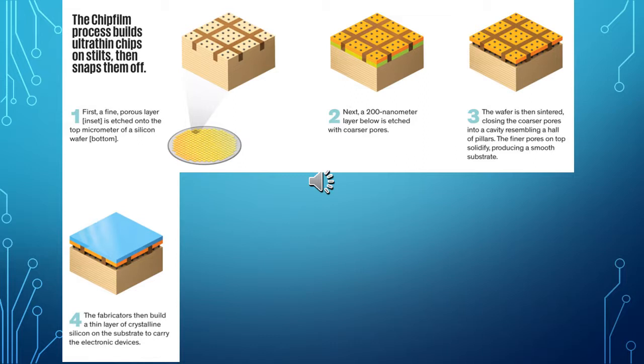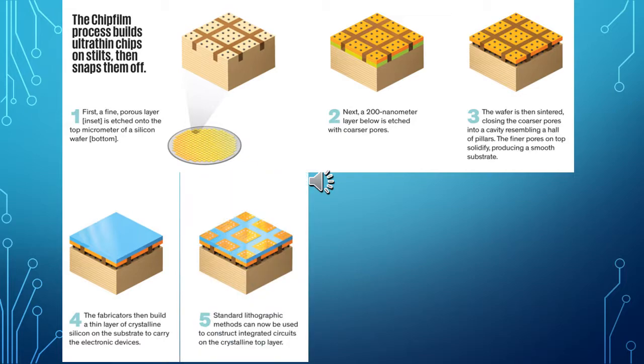Next, the fabricators build a thin layer of crystalline silicon on the substrate which carries the electronic devices. Almost all the electronic devices are located on this top layer, and it is this top layer which is of utmost importance to us. Integrated circuits are now constructed on the top layer of the crystalline silicon using standard lithographic methods. Dry etching is usually preferred as it induces less crystal damage compared to wet etching.